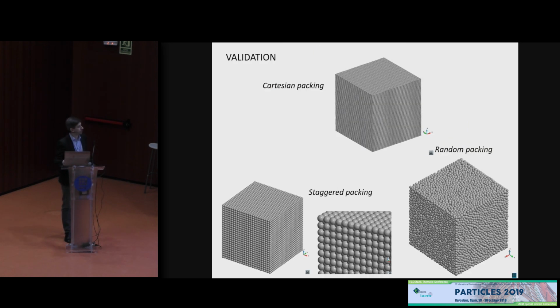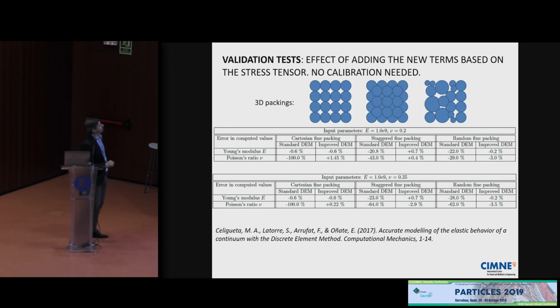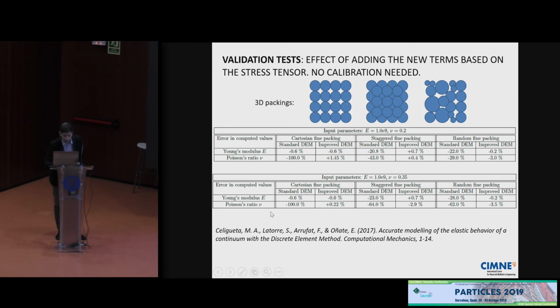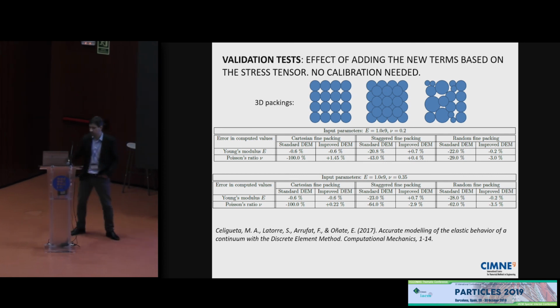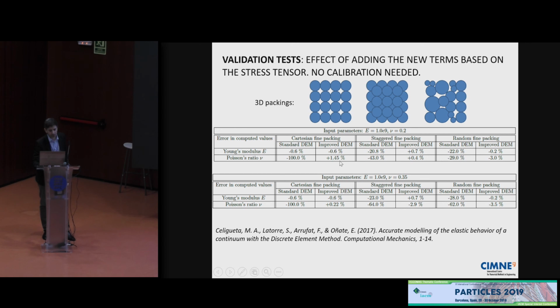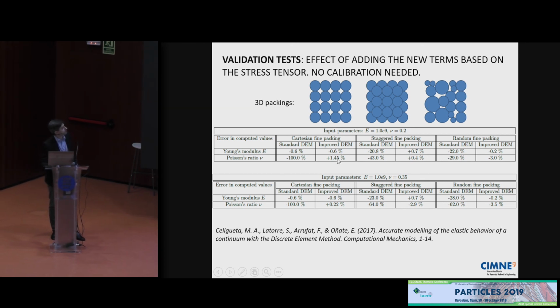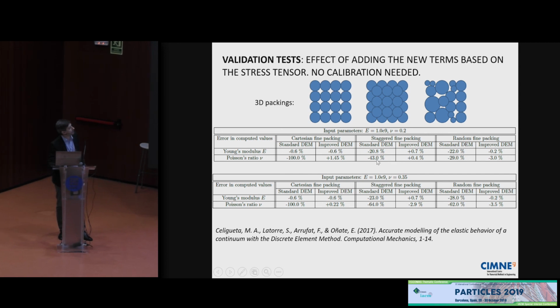Random packing, Cartesian packing, and staggered packing. Those are the tests that we did in the publication. And we can see here, for example, that, let's see if the mouse works well. Yeah, this error is what you get when you use the standard DEM, 100% of error. But if you use the extra terms with Cartesian fine packing, you get only 1.5%. For staggered packing, you go from 43% to 0.4. And for random packing, you go from almost 30% to 3%. So there's still some kind of heterogeneities that are putting some error, but at least we were very happy that we could capture those elastic properties without calibrating.